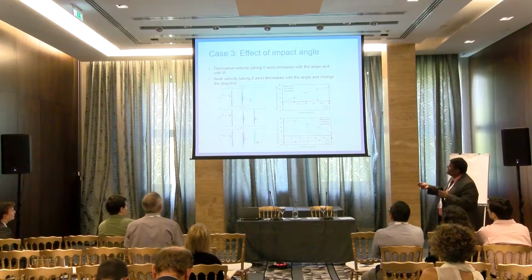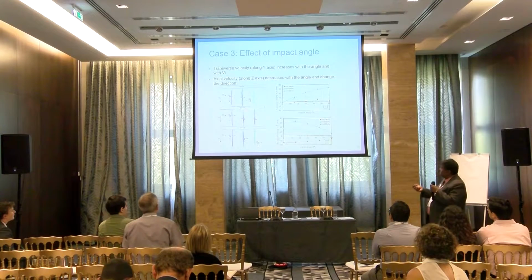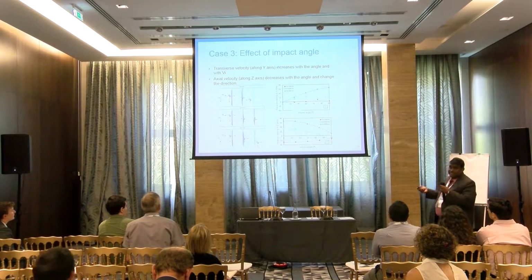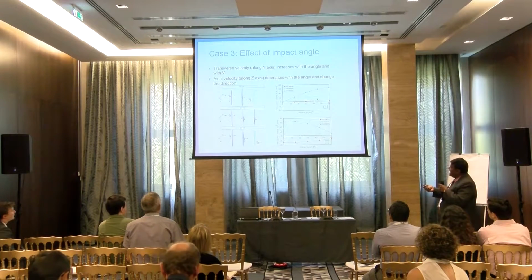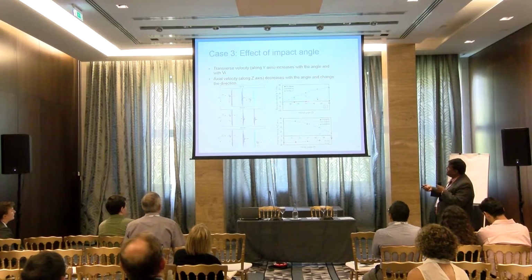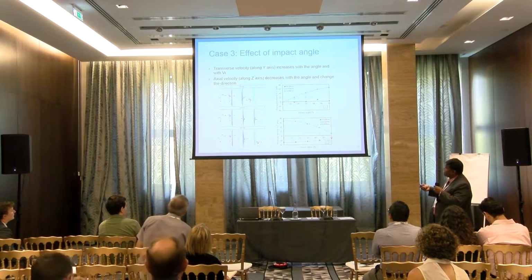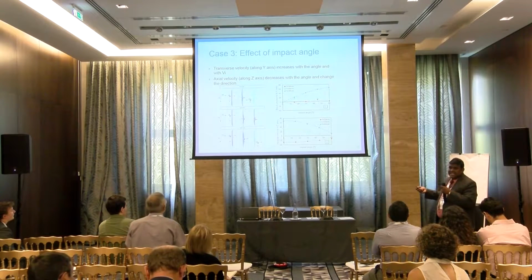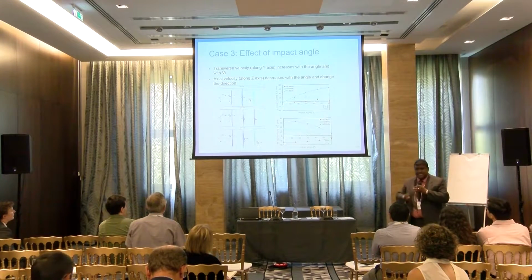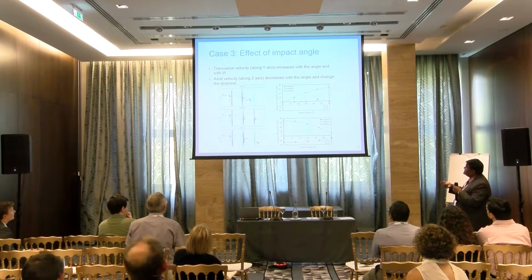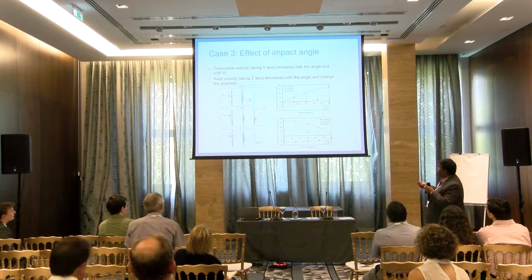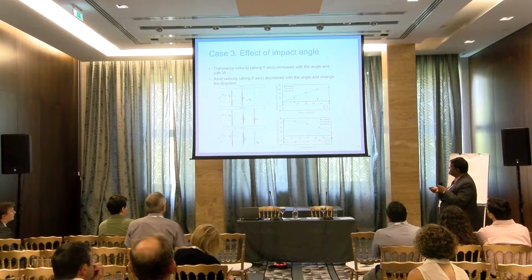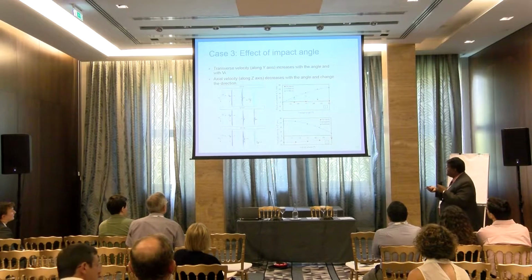But what really happens when the impact occurs? We have 3 different cases. If your initial velocity Vi, which is the magnitude, is low enough, less than the critical velocity, then after the impact the transverse velocity will reduce and the axial velocity will be reversed, which is like a rebound, but the projectile is slowed down in the transverse direction. And this is what you can see in this residual velocity plot. When your velocity is 30 meters per second, the Y velocity is reduced, but the Z velocity is actually reversed, so it is negative, and the projectile never penetrates the fabric. So we are in the safe zone.